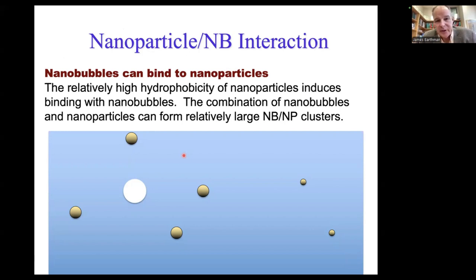Anyway, what I was really interested in was not so much the nanobubbles themselves, but how they interact with nanoparticles. And this is what I was interested in. Nanoparticles have a very high surface tension as well. And if they encounter a nanobubble, they will bind to it. The hydrophobic forces can actually overcome differences in charge between the nanobubble and the nanoparticle. In other words, if I have a particle that's minus 5 millivolts, it'll still bind to our nanobubbles, which are minus 30 millivolts or more.